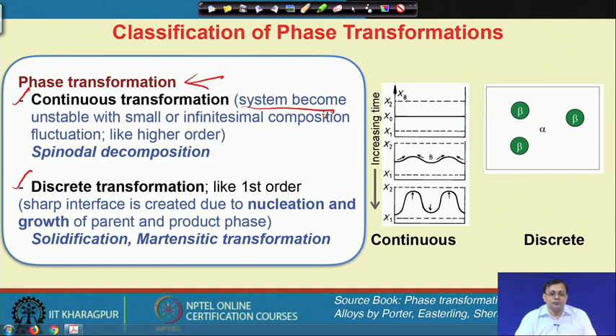You must have heard of spinodal decomposition in your undergraduate days. However, we will again discuss the same. In case of spinodal decomposition, we have a solid solution which has an average composition of x 0. If we make a very little composition fluctuation, meaning if we deplete an area, then definitely there will be enrichment, because the atoms will move to the nearby site. In such a case, there will be a localized fluctuation in the composition of the system, and that always decreases the free energy of the system, meaning the system always goes in favor of making the composition fluctuation.